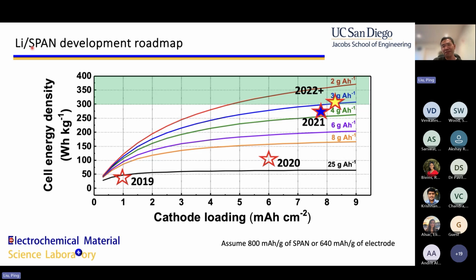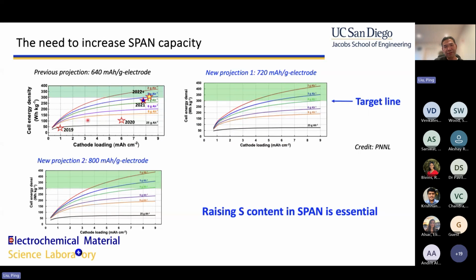I used to work in industry, and for every technology we develop, there has to be a roadmap. So what's plotted here is energy density as a function of cathode loading. We need to make a very thick cathode. And these numbers are the amount of electrolyte we add. We need to add a very tiny amount of electrolyte in order to produce a high energy density cell. The bottom line is, however, our SPAN material, as stable as it is, the capacity is a little too low. So if you redo the modeling, but assume the electrode has higher capacity, then obviously the energy density of the cell will increase.